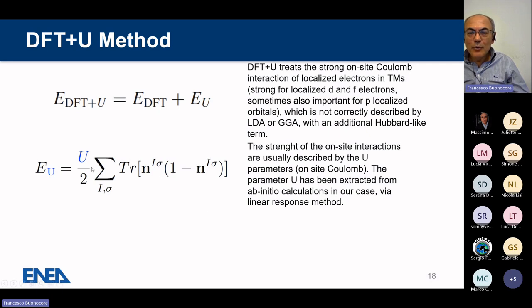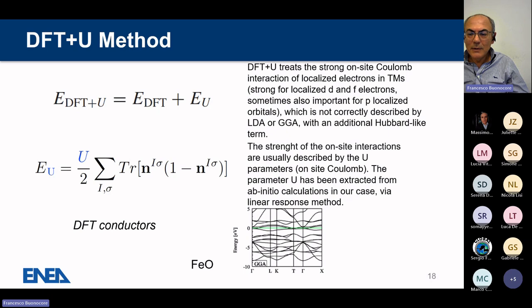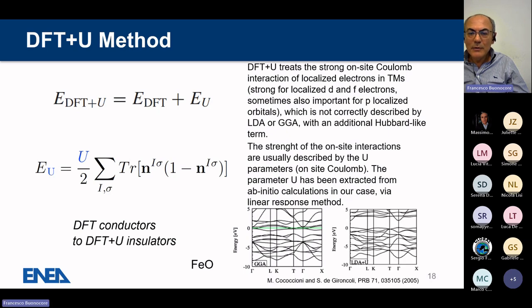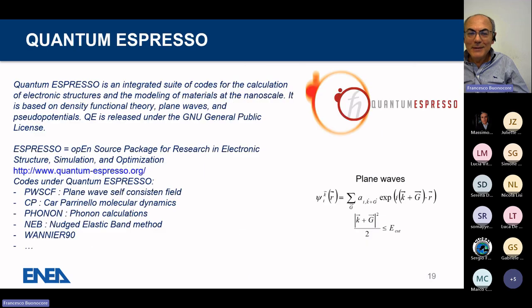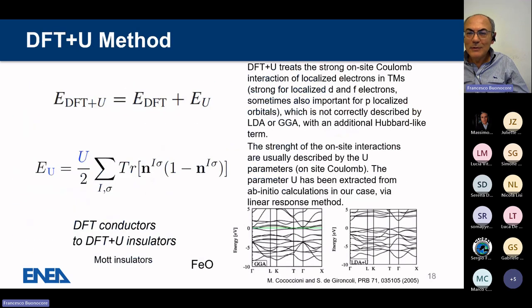So we calculated the U for some systems that we then used for the other crystals we modeled in our theory. And anyway, all the crystals not well described by DFT are predicted as metals, but really they are insulators, called Mott insulators. So we are quite unlucky, because most of the systems we are interested in for cathode materials are Mott insulators. So we need this correction to the theory.